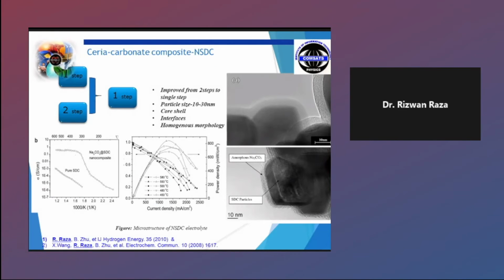In that project, if we compare, as I mentioned, yttria stabilized zirconia can get an ionic conductivity at 1000 degrees, but after doped cerium material, it can be reduced to 700 degrees. But using this technology, using nanocomposites, 0.1 Siemens per centimeter can be achieved at very, very low temperature as compared to conventional electrolyte material. Another thing is to introduce nanocomposite, meaning nano can enhance the stability and composite can enhance the conductivity of that material. Using these techniques, we started from this electrolyte material, and we prepared a ceria carbonate.